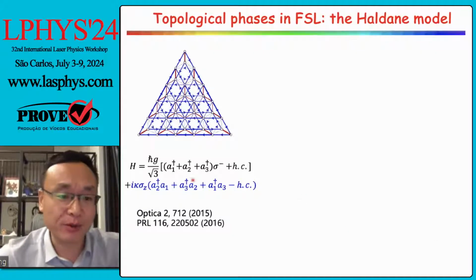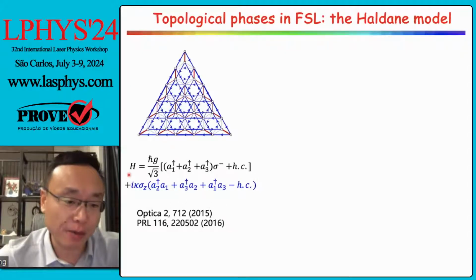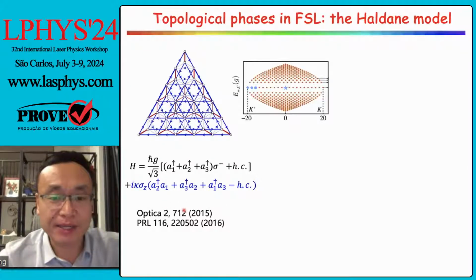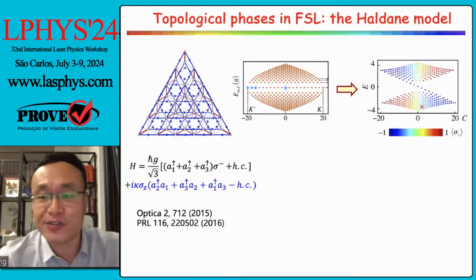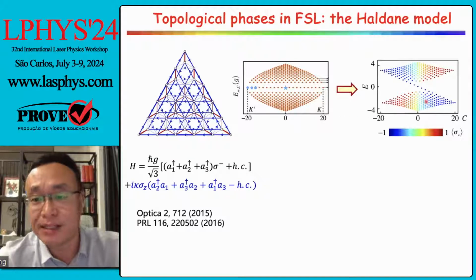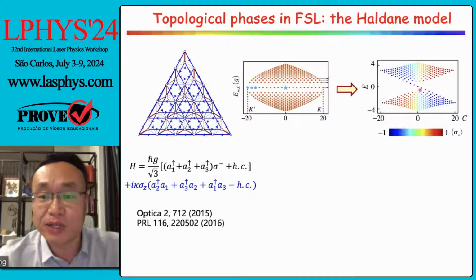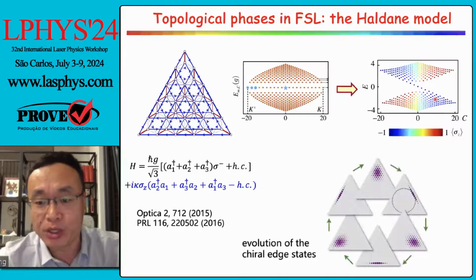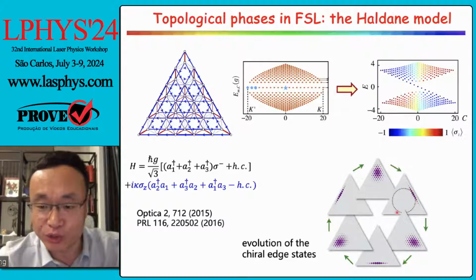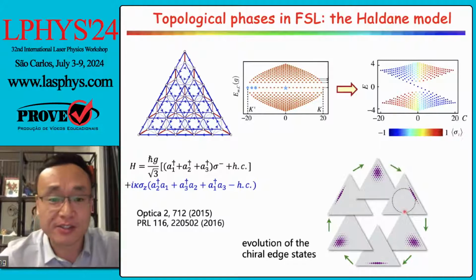And we can actually build a more complicated model, just the one I have mentioned at the beginning of the talk, the Haldane model. We can introduce next to nearest neighbor hoppings in this form. And what will happen is that the band structure, the flat bands, are going to be transformed to this structure. All the positive Landau levels become a single band. All the negative Landau levels become another band. And the 0th Landau level becomes edge states connecting these two bands. And we can see it is chiral, because if you prepare an initial state on the topological edge, you're going to find the state rotating around in a circle, which is the topological edge of the system.